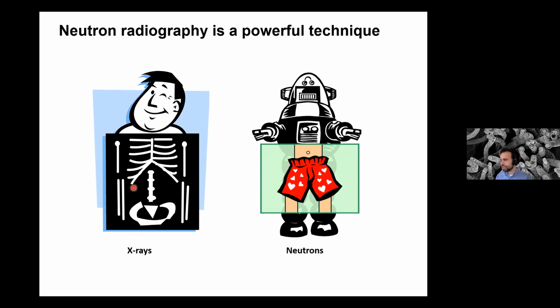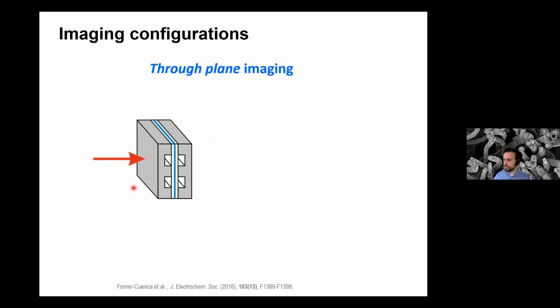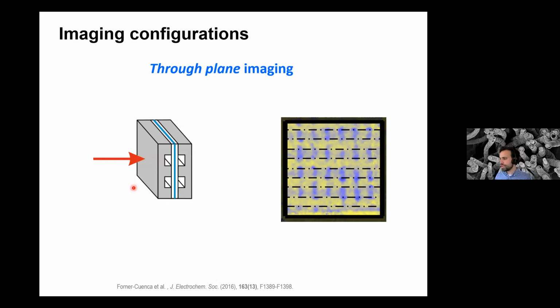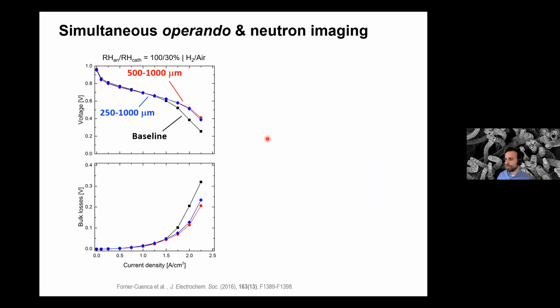And this is, of course, just a sort of a joke representation, but the idea is that every electrochemical cell is composed of metals and carbons and polymers, and that is all nearly transparent for the neutron beam. And what you can see inside is to look at lighter materials such as water, lithium, boron, and that's why neutron radiography is a very powerful technique to look at, for example, multi-phase transport. Okay, and that's what I do here. I look at the fuel cell during operation, and I can differentiate and see water locations under the ribs and under the channels. So it allows us to do a local quantification of the water distribution.